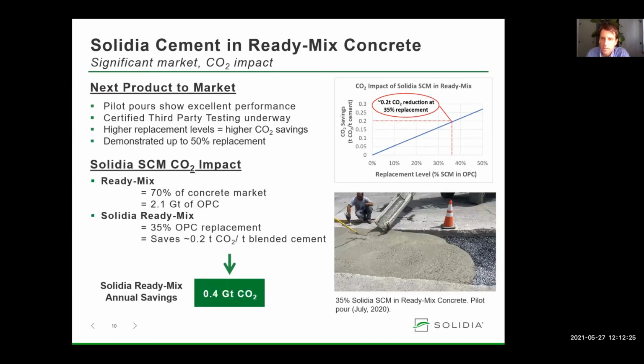Solidia SCM is currently under development and will soon enter the market. We have already demonstrated this technology with pilot scale test pours, shown here in the photo, and have seen excellent performance both in terms of mixing, forming, and final properties. Evaluation and testing are underway at certified third-party and academic labs. Since Solidia SCM is used as a partial replacement for OPC, higher replacement levels lead to increased CO2 savings. We have demonstrated successful replacement levels up to and including 50%.